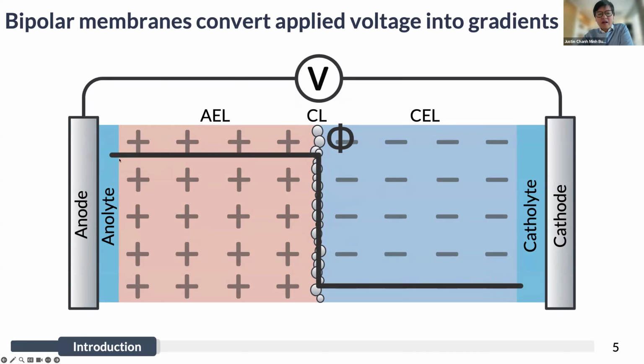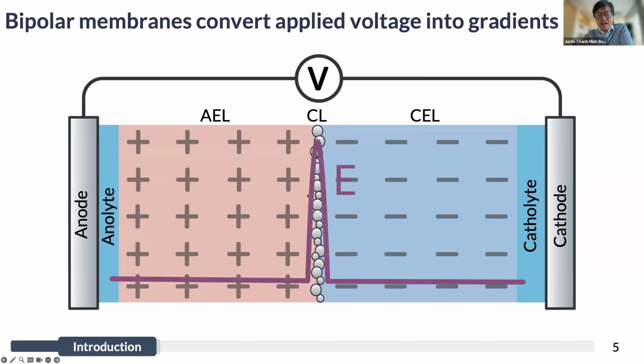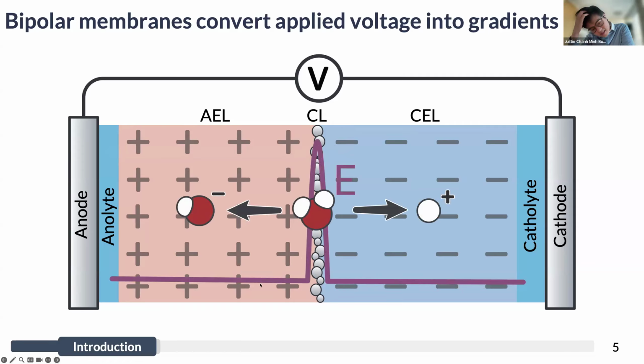When I apply voltage across the membrane, I get an electrostatic potential drop through the polymer that looks something like this, where because you have a lot of charge in the individual polymers, all of that electrostatic potential drop is screened at the interface between the two oppositely charged polymer layers. This creates a really large electric field, and that electric field is sufficient to drive chemistry at this interface when paired with this catalyst layer. And the biggest example of a reaction that you can drive at this interface is the dissociation of water into protons and hydroxides.